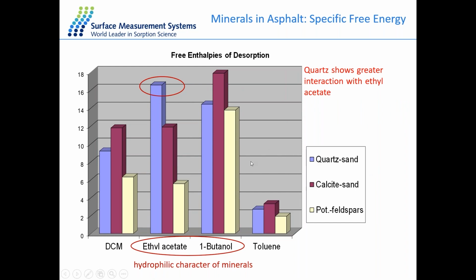On the other hand, we have our quartz sand shown in purple, and this sample has a stronger affinity with ethyl acetate. Because ethyl acetate is a very weak Lewis base, this suggests that this sample is interacting with some sites on the ethyl acetate, which has a high affinity with these functional groups as opposed to the butanol. So it's interesting to understand the behavior of different probes with our materials. And of course, you can change the polar probes you wish to use, which may be more appropriate to the understanding of your material.